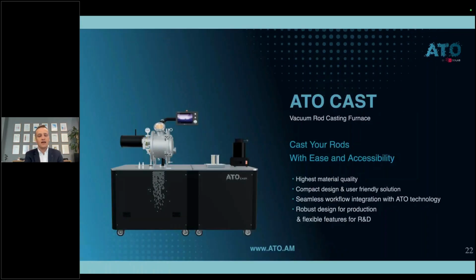An additional machine which can help us to improve the research or the efficiency of the process is our AtoCast. This is a self-sufficient induction vacuum casting machine and furnace which allows you to cast your rods. But the biggest difference from the induction melting system itself is the fact that we do not have any atomization process here. This is only a vacuum casting furnace. But in that case, we can achieve a melting point for the materials up to 3000 degrees. That's why we can work with multiple different scenarios depending on the customer needs.